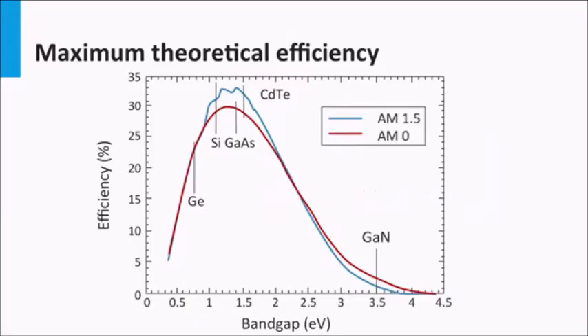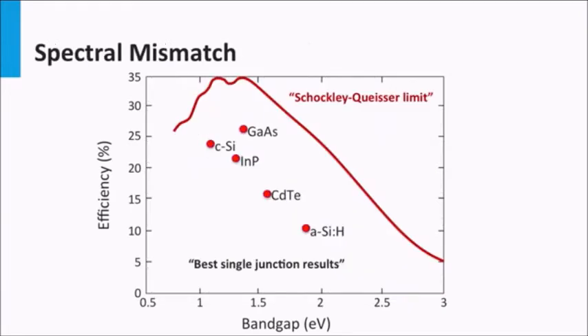For single junction solar cells, you can see that semiconductor materials such as silicon, gallium arsenide and cadmium telluride have an optimum bandgap. However, if we look at the record efficiencies of solar cells, they are all below the Shockley-Queisser limit. The reason for this is that additional optical losses like reflection and parasitic absorption, and electrical losses like Shockley-Read-Hall and Auger recombination are not considered. The Shockley-Queisser limit only considers radiative recombination.